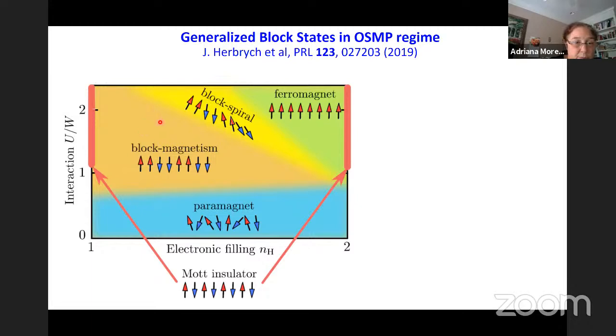We decided to look at the phase diagram as a function of electron filling and as a function of the Hubbard repulsion, keeping the J-Hund equal to 1/4 of U.